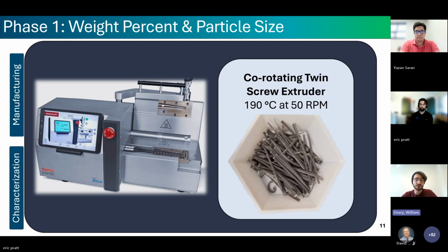This machine is just a benchtop twin screw compounding extruder, which is also used in industrial settings. The only major difference between the lab scale and industrial scale extruders is the temperature control along the screws and the cooling and control of the extruded material. So for this lab scale extruder, we only had 1 temperature set point, and our cooling setup was a simple conveyor belt that was placed next to the output of the extruder.